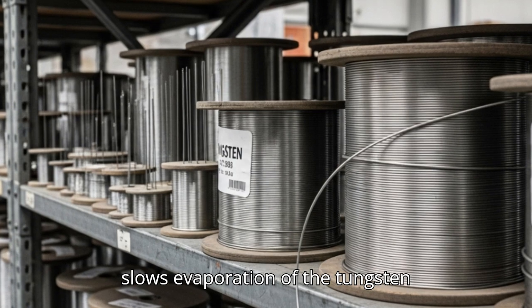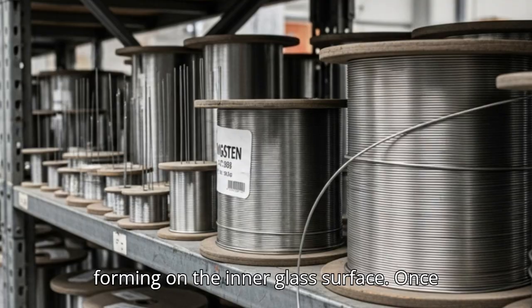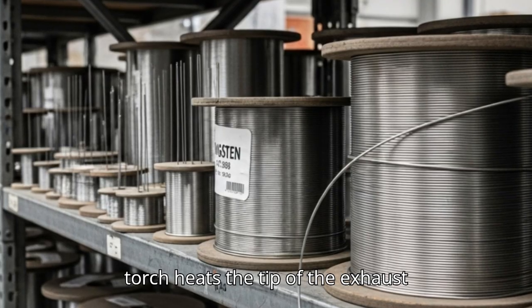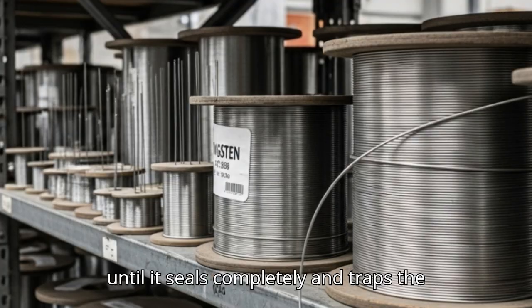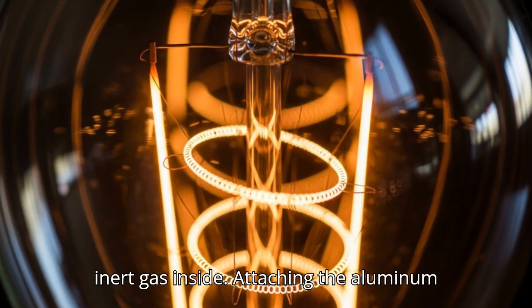This gas blend slows the evaporation of the tungsten filament and prevents dark residue from forming on the inner glass surface. Once the correct pressure is reached, a gas torch heats the tip of the exhaust tube to over 1,800 degrees Fahrenheit, melting the glass until it seals completely and traps the inert gas inside.